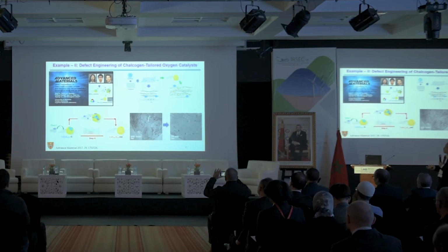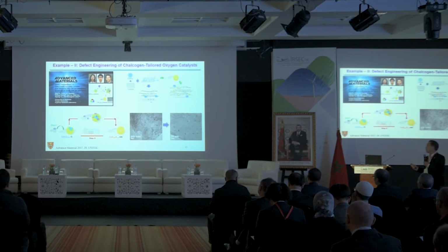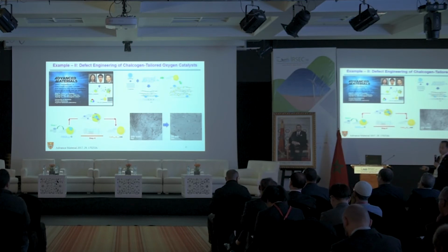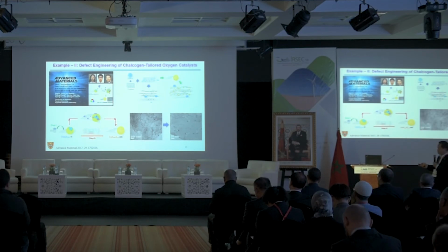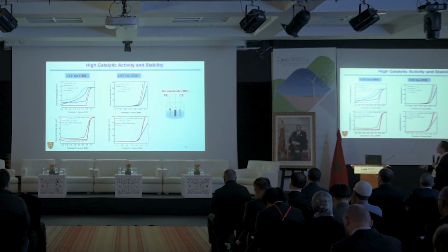Like this catalyst, by this synthesis methodology, we successfully get doped porous graphene with cobalt, a chalcogen-tailored oxygen catalyst. The porous graphene itself has defects. These oxygen defects also provide activity, and because it's porous, it makes the mass transport easier during the reaction. So with this catalyst, we were also successful.